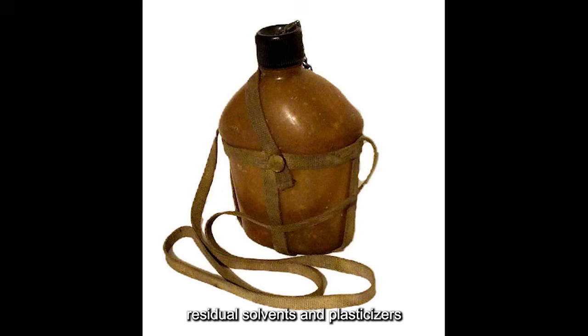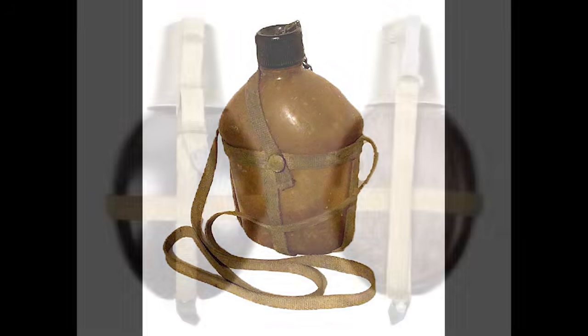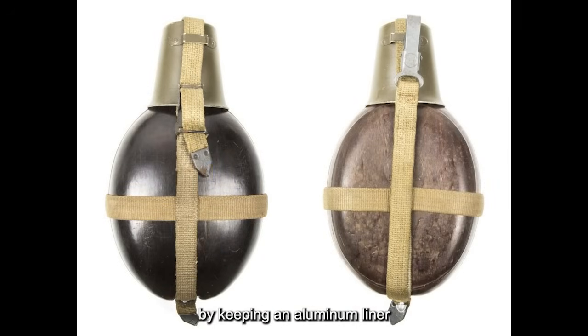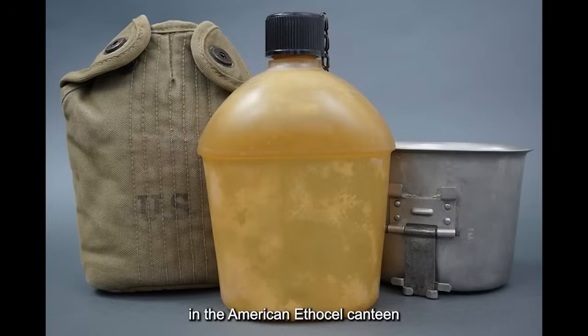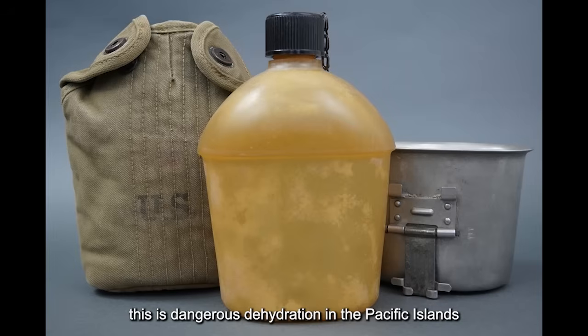Residual solvents and plasticizers trapped in the Ethocel during manufacturing begin dissolving into the water at accelerated rates. This is what the Germans avoided by keeping an aluminum liner. The water in a coconut canteen never touched the phenolic resin. In the American Ethocel canteen, there's nothing between the water and the unstable plastic. Troops start feeling nauseated. Many refuse to drink even in extreme heat. This is dangerous. Dehydration in the Pacific Islands could incapacitate a Marine faster than enemy fire.